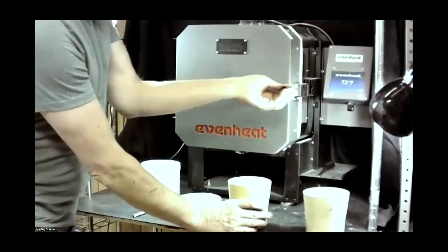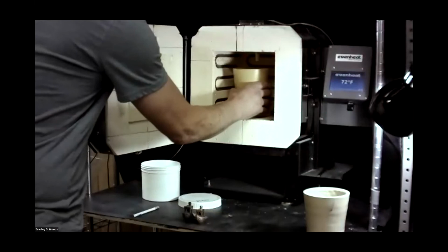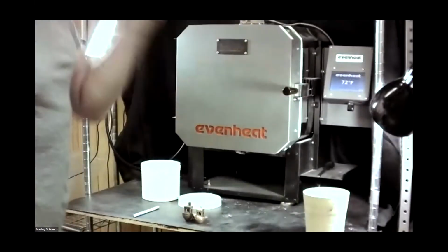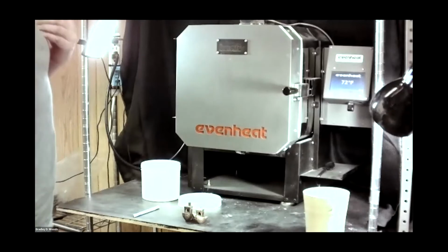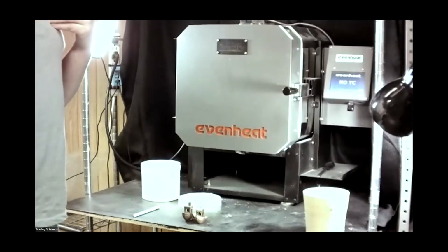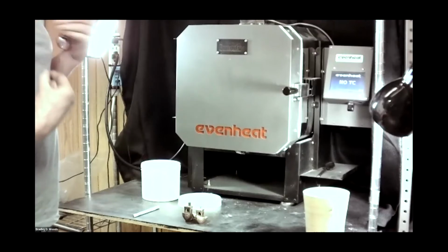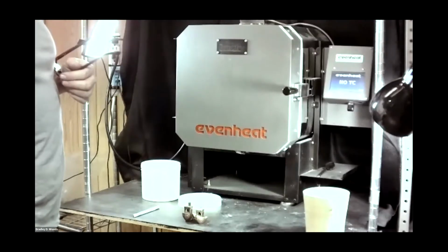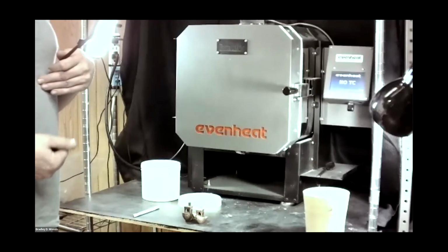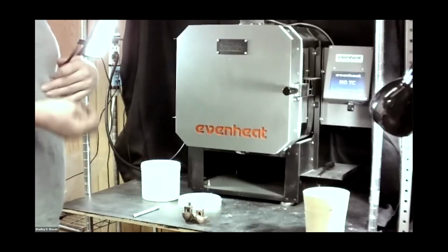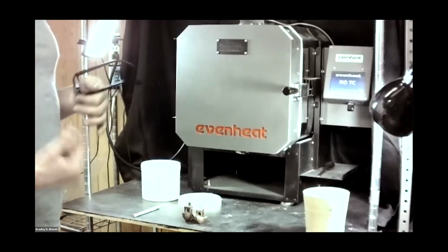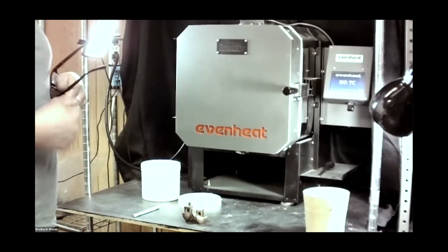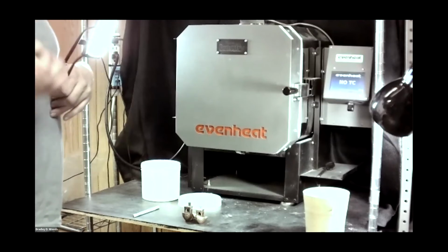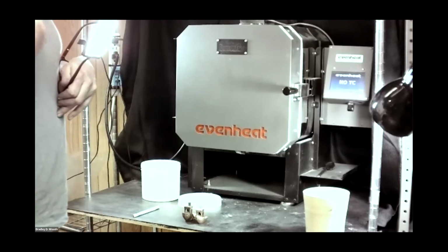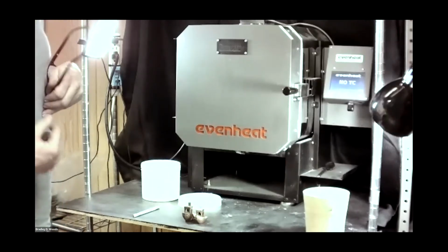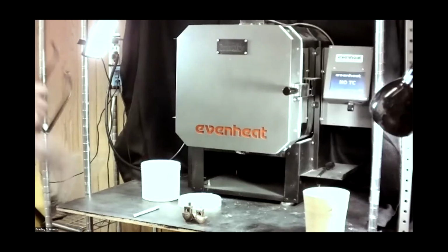Next step is to put it in the kiln and execute the debind program for copper in this case. And we've greatly simplified the debind recipe, we call it. So essentially, you're just warming the temperature up to about 400 degrees as fast as you want. And then over however many hours it takes, raise it to the sintering temperature at a rate of 100 degrees Fahrenheit per hour. So this is not a fast process, but it works really, really consistently, and you will get a successful result.